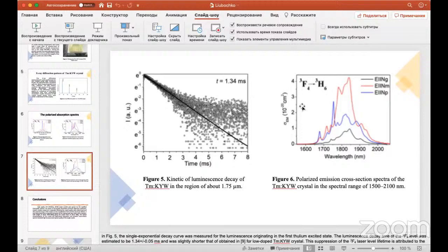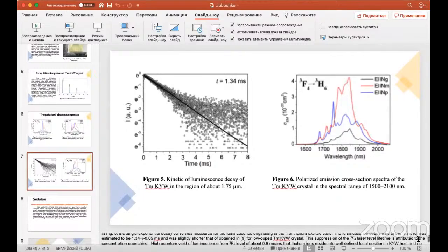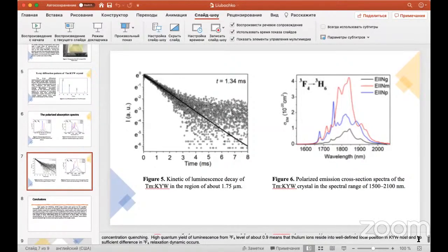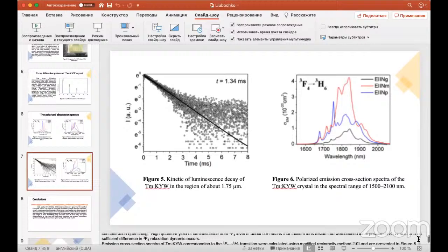1.34 plus minus 0.05 millisecond, and was slightly shorter than that obtained for the low doped TM:KYW crystal. This suppression of the 3F4 laser level lifetime is attributed to the concentration quenching. The high quantum yield of luminescence from the 3F4 level of about 0.9 means that the thulium ions are placed into a well-defined local position in the KYW host and no significant dependence in 3F4 relaxation dynamics occurs.